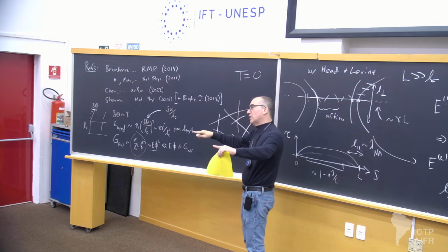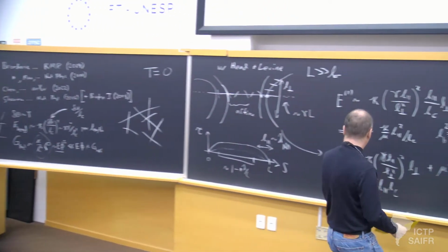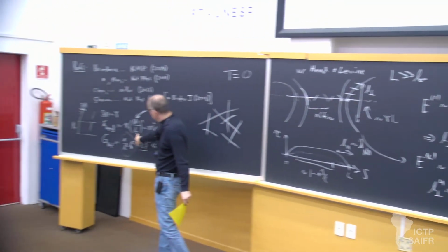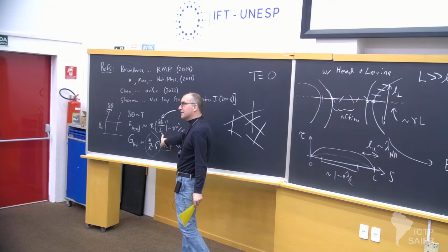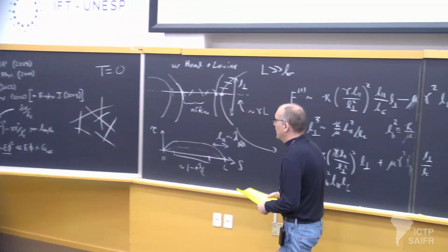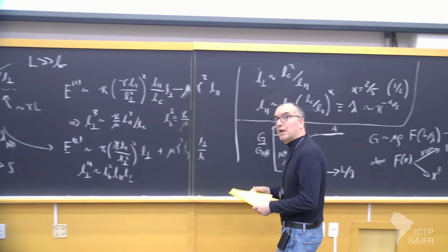That distribution of cross-link distance, because of this strong inverse dependence on cross-link distance, affects things if that distribution is broad. So the network architecture does appear, and that's why I would not call it universal.